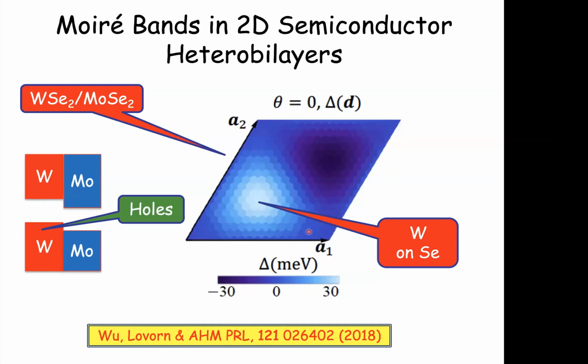But when we originally derived the interlayer tunneling model, we replaced all of the momenta by the Brillouin zone corner momenta. And so we ignored the dependence of interlayer tunneling on momentum. But we know that the Fourier transform of the real space interlayer tunneling gets weaker at larger momentum. So you can use one number to characterize the shape of the curve. And that's the approach that we've taken.